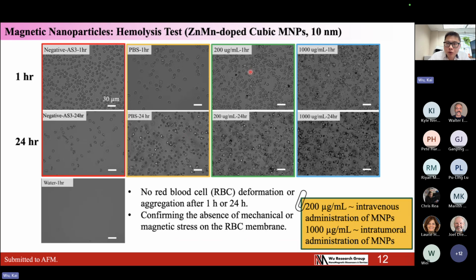We vary the concentration of the particles from 200 microgram per milliliter to 1000 microgram per milliliter. So this low concentration mimics the intravenous administration of particles into the blood vein. The 1000 microgram per milliliter mimics when we inject the particle directly into the tumor, which we call intratumoral administration of particles. And you can see that for the zinc manganese doped cubic particles with 10 nanometer size, we do not see blood cell deformation of the shape or aggregation of blood cells after 1 to 24 hours of incubation. This confirms that this nanoparticle will not generate any mechanical or magnetic stress to the red blood cell membrane, which is safe for the intravenous or intratumoral injection.